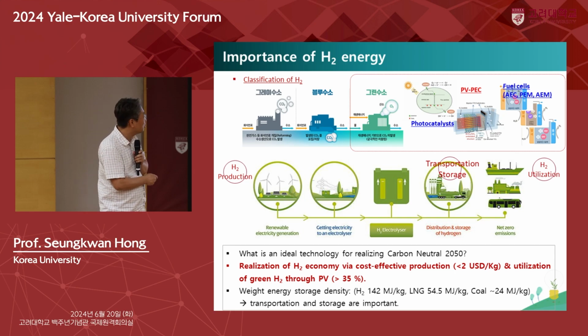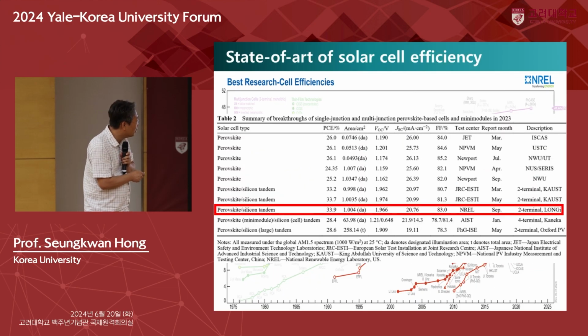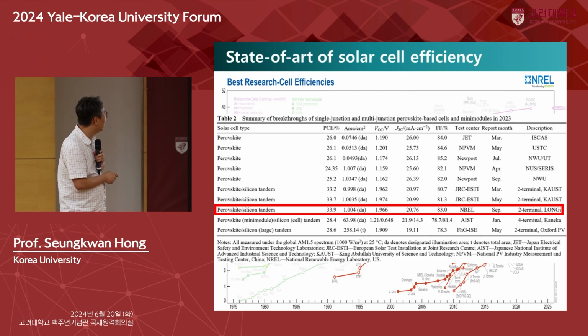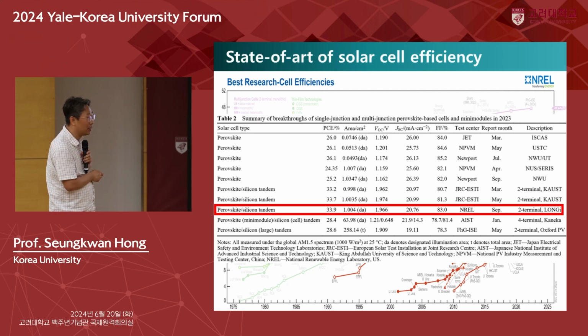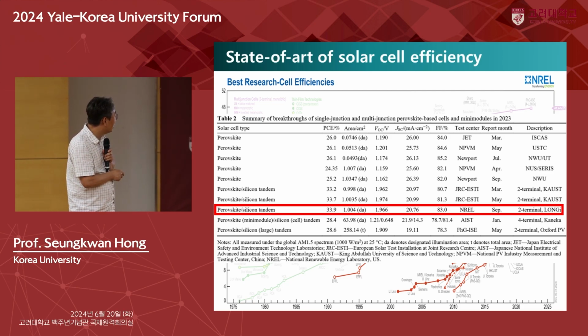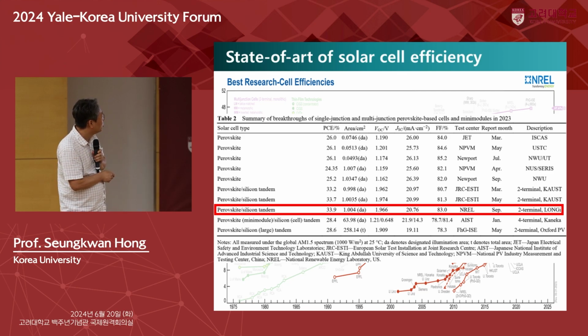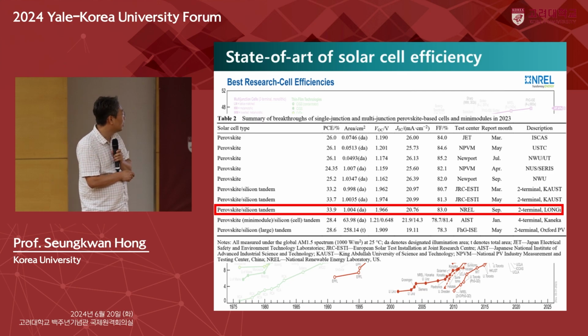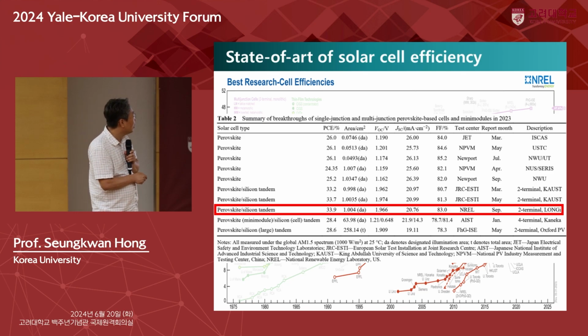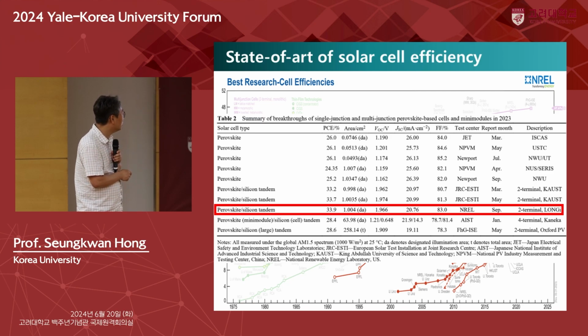So Dr. No already showed this one, but we are focused on the tandem system. More specifically, LONGi, the Chinese company, reported a record efficiency of about 33.9%. The size is about 1 square centimeter, and the open circuit voltage is about 1.966 V, and the short circuit current density is 20.76. And the fill factor is very high, 83. And about several days ago, they reported that the efficiency is more than 34%. So the efficiency is very high.